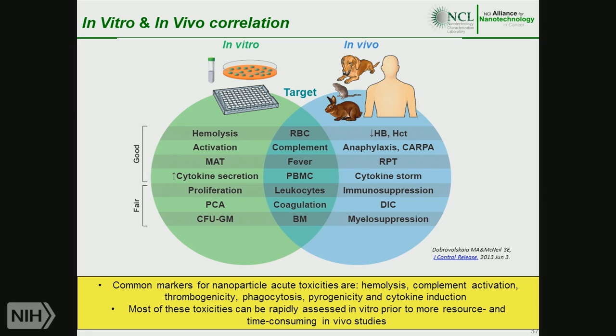For example, CFU-GM allows us to look at the bone marrow toxicity, which would correlate in vivo with myelosuppression. So we may see a decrease in CFU-GM counts in vitro, because in vitro there are only bone marrow cells and the particle. But if we inject this material in vivo, it may not distribute to the bone marrow. Then in vitro results become irrelevant. But if the material does distribute to the bone marrow after IV administration in vivo, then in vitro data correlate with in vivo data.